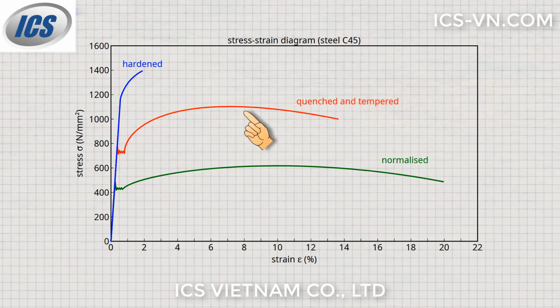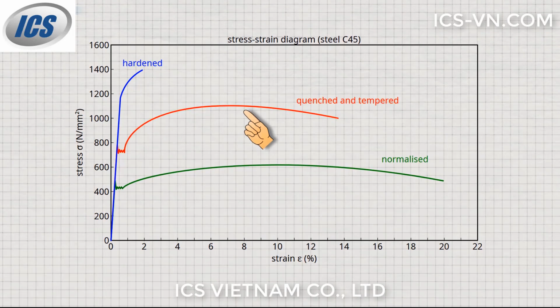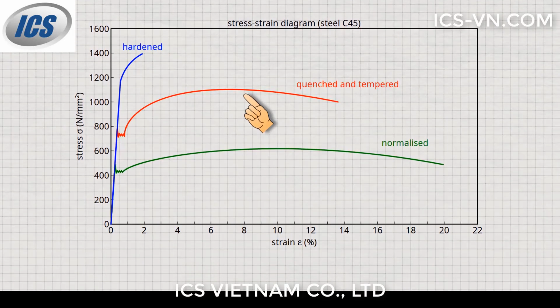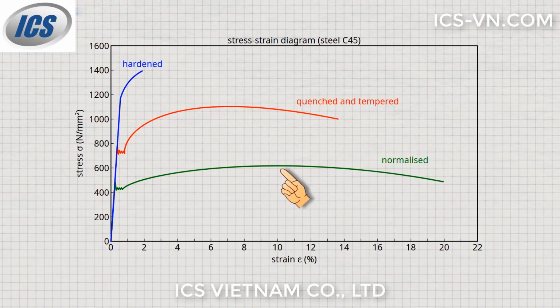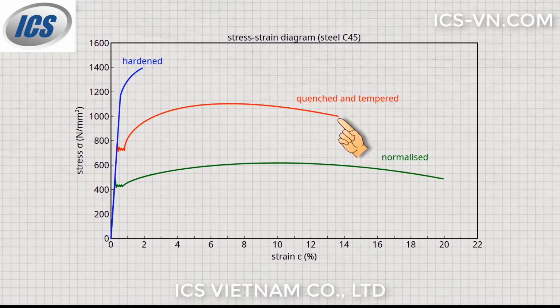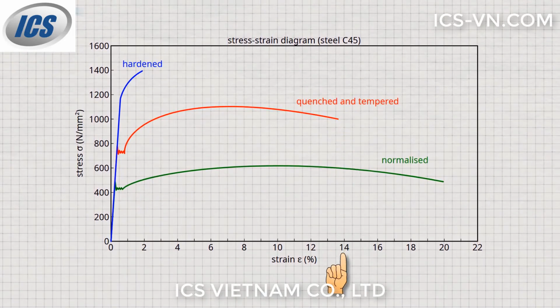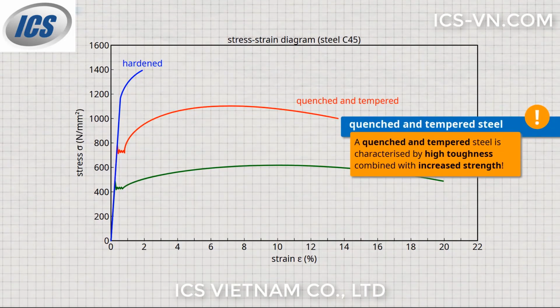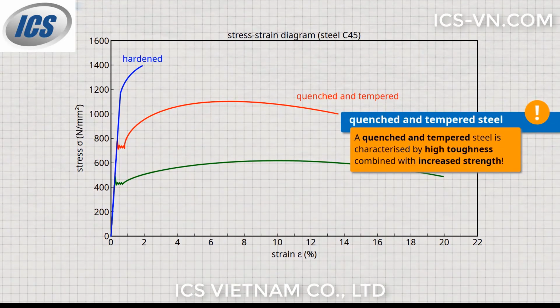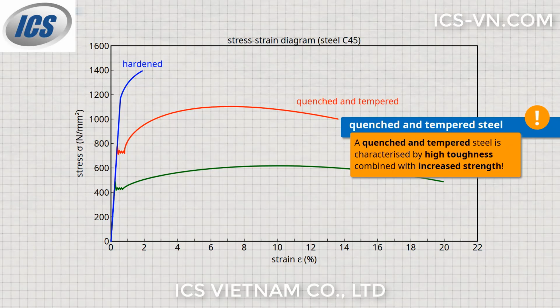Quenched and tempered steel is significantly tougher than the hardened condition and can therefore be deformed to a much greater extent. Strength is also significantly increased compared to the normalized state. The yield point and tensile strength have almost doubled as a result of quenching and tempering, while the elongation at fracture is still relatively high at 14%, so the quenched and tempered steel retains high toughness. So note, a quenched and tempered steel is characterized by high toughness combined with increased strength.